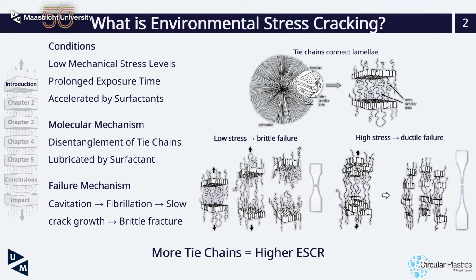Environmental stress cracking occurs exactly under the same conditions. Relatively low mechanical stress applied over a long period of time, combined with exposure to chemicals such as surfactants in detergents. This gradually leads to cavitation, fibrillation, and eventually brittle fracture. The role of tie chains in this failure mechanism is therefore critical. In simpler terms, if you have more tie chains in your polymer, it will have higher ESCR.